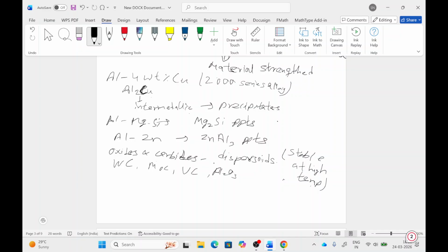But if we talk about precipitates, they dissolve at high temperature. So their strength is only increased for a specific service temperature regime. The precipitates have some service temperature region in which the strength is higher, but dispersoids are stable at high temperature, so they will provide more strengthening in the metal.